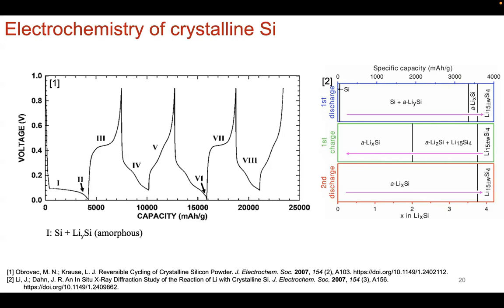What you see here more is what one could consider sloping, plateau-ish, but mostly sloping. And then here in subsequent cycles, you see really sloping. So now it's indicative that you're forming a single phase intermediate and that you're not going through a two-phase region. Okay. So what's been proposed based on characterization and the electrochemistry as well is that you're starting with silicon in this one phase going to that of this amorphous LiySi phase. And then from there, at the end here, this point 2, you're forming from the amorphous lithiated silicon the metastable Li15Si4. So that's the first discharge that you see.